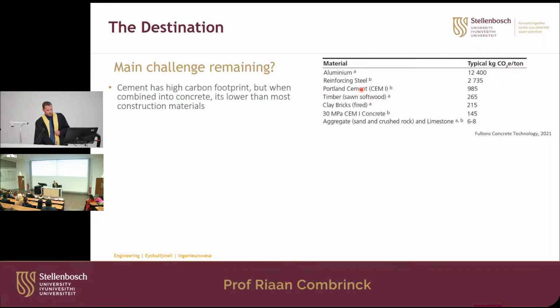And the Portland cement is also up there. It's about 1,000, so it's quite high. But once you start adding aggregate, which is stone and crushed rock and limestone, which is quite low, you get a concrete, which sits about here, which is about 145. So concrete itself is sustainable. It's the cement that we are adding, which is the problem.